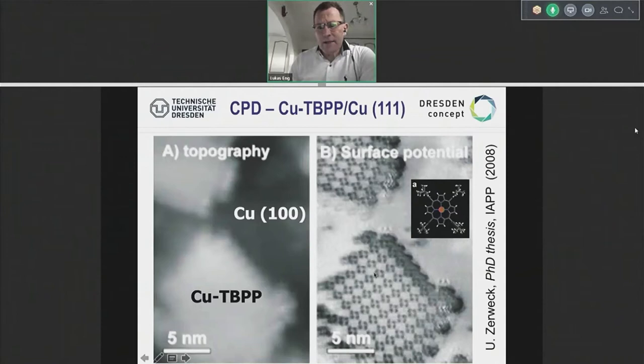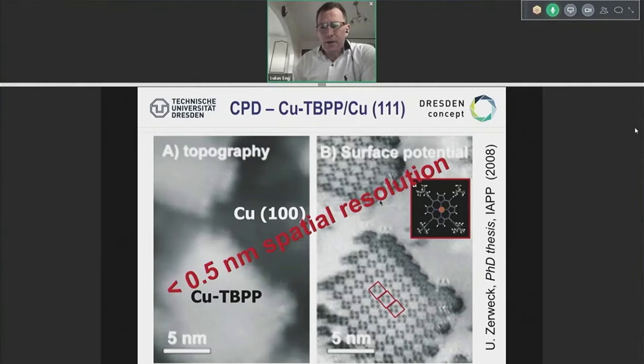But if you look again on this Kelvin signal, you have a much better insight into the system, simply because you see, in fact, the four legs of one single molecule, 1, 2, 3, 4, which are charged negatively. So it's these butyl legs in the porphyrin that are taking up the electrons. So this means that this delta phi resolution, the work function resolution that we find here, is on the same order like an STM. So it's really equally good. And that's some kind of work we would like to work on with you guys too.